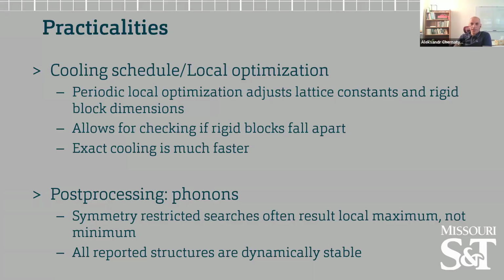One other important thing to point out is any symmetry restricted searches quite often result in a local maximum rather than a local minimum, or maybe a saddle point on your phase space. And so dynamical stability of your structures is important to assess. Fortunately, these days, calculating phonons on something which has 20, 30 atoms per primitive cell is not extremely difficult. So all the structures that I will report today pass that filter, and all of them have a stable phonon structure. I will not show phonon band structures because we don't really use them for anything useful other than one little piece. But this is to ensure that the structures are dynamically stable.